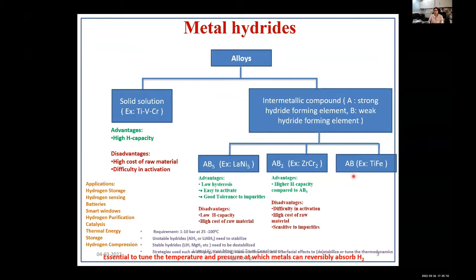Another class like AB, where the cost is comparatively lower and they can work close to room temperature, but the problem remains again the difficulty in activation. Other than the intermetallics, there could be solid solutions. The well-known one, titanium, vanadium, chromium, has a higher capacity, but then the cost again is a challenge. And then the problem associated is difficulty in activation.